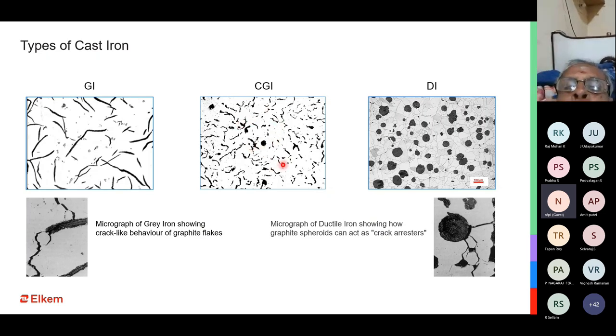So CG iron can be of different grades, with a nodularity of anywhere between 15%, 20%, 30% or so. So it will not be like 85, 90 as in ductile iron, and it will also not be zero like gray iron. It will be somewhere in between.